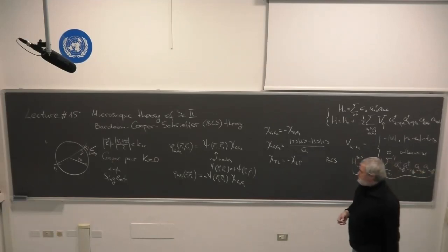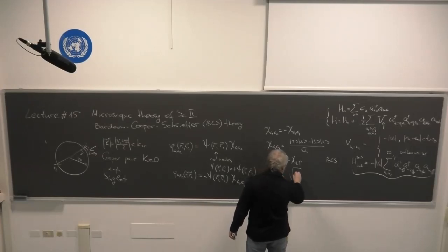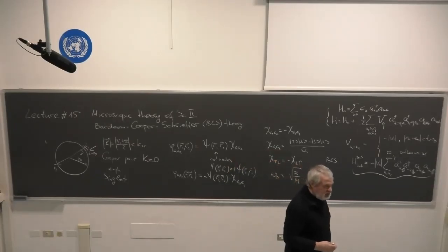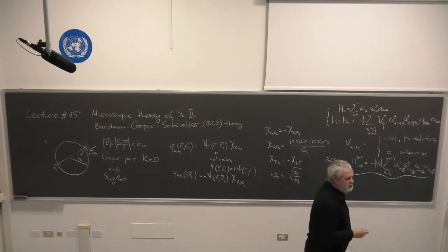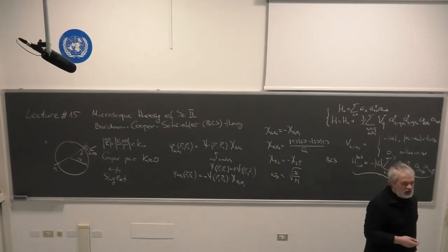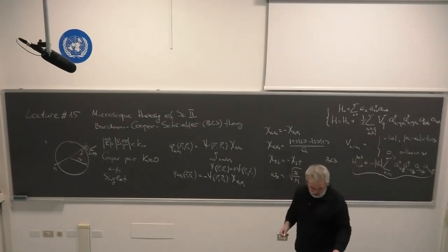And then it immediately came to mind that since the Debye frequency is, say, some modulus of stiffness K divided by M, and the Debye frequency satisfies this criterion, people started to think that maybe phonons are involved. Therefore this treatment of phonons, and the discovery that phonons can mediate the pairing, results in attractive interaction for small energy transfer defined by this condition.